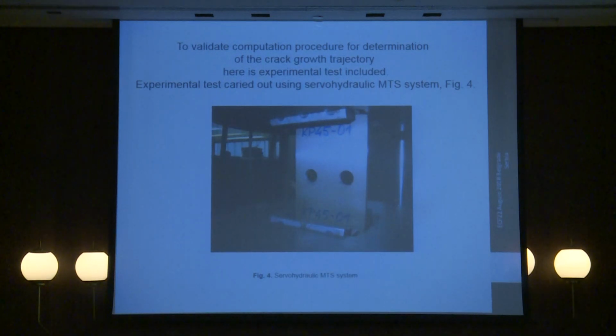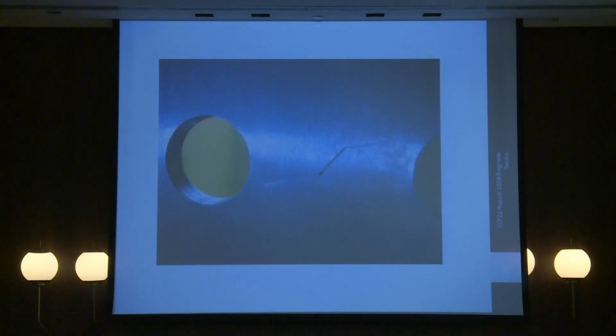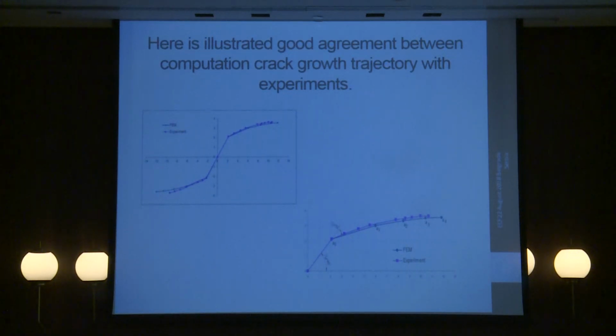To validate this computational method, we used experimental testing. For experimental testing, we use the servo-hydraulic MTS system. It's in this figure, and we introduce the load in this specimen, and then we determine the crack length experimentally. This is the detailed view. After that, we need to compare the results we get using the finite element method and using experimental testing. As you can see on these two diagrams, we have very good agreement between the results of the experiment and the finite element method.